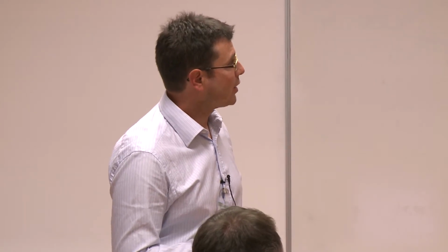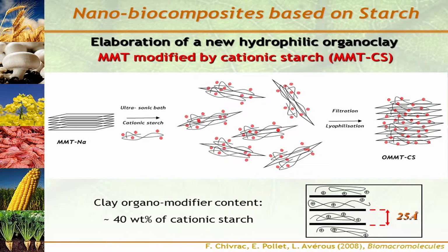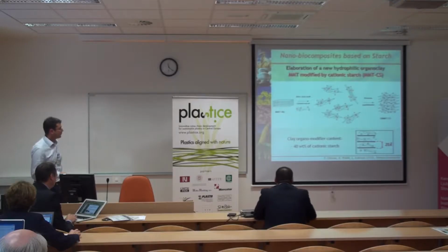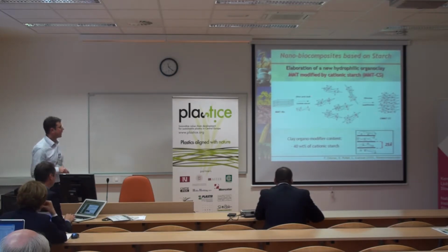So this is done in water using ultrasonic baths. In water, you separate all the clay platelets. The cationic starch adsorbs on the negatively charged clay platelets, and after filtration and lyophilization, you recover your clay organomodified with cationic starch, which has a stacked structure like here. This allows having cationic starch chains between the clay platelets, so we are hoping for better compatibility with the starch matrix, and we start with a higher initial interlayer spacing, around 25 angstroms, so we hope that the intercalation of the starch molecules will be easier when processing and adding this organomodified clay to the starch matrix.